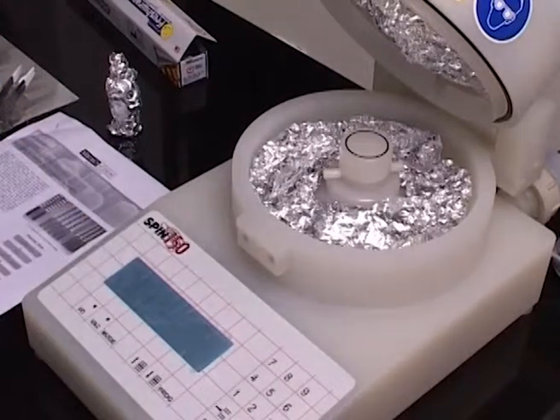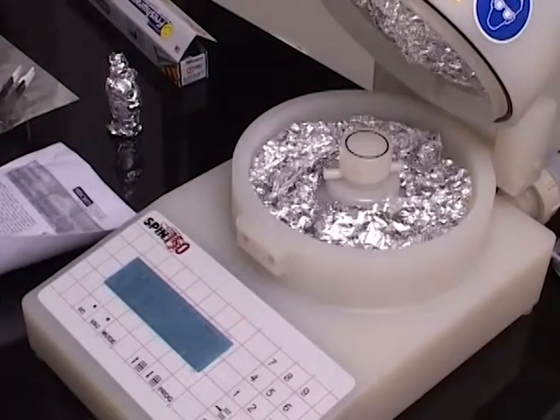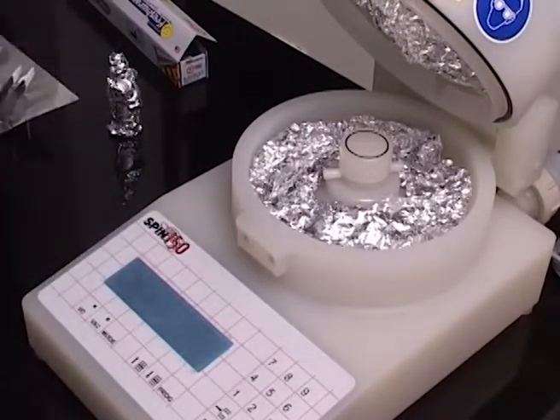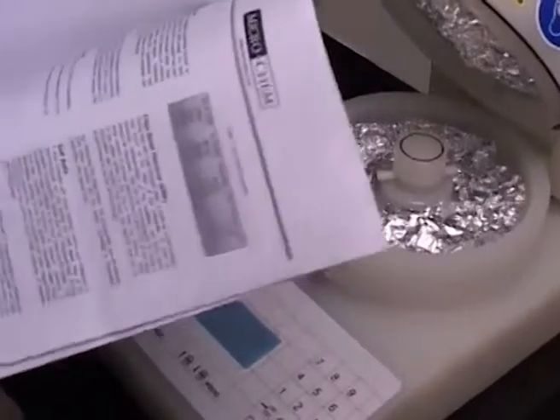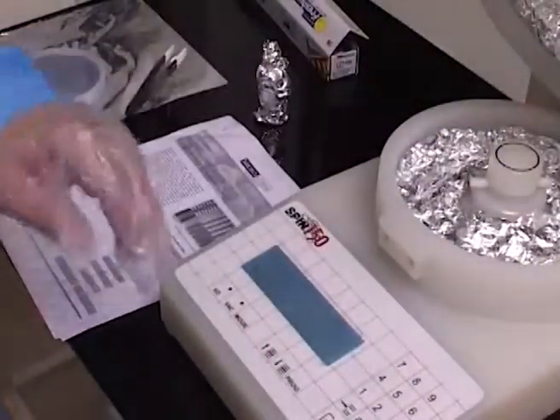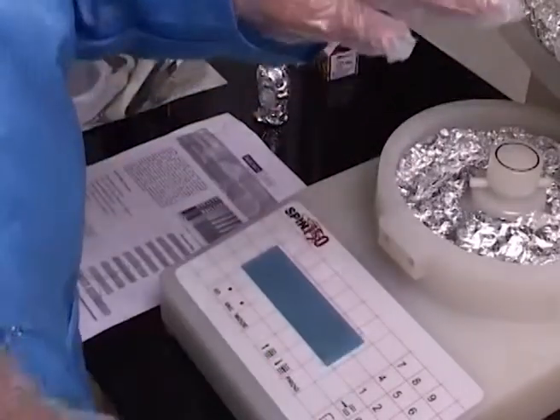In this particular example, as per the resist manufacturer specifications, the spin speed that we are using is about 3500 RPM, and the spin speed has to be attained with an acceleration of about 300 RPM per second. It also mentions that you have to hold at that spin speed for close to 90 seconds for the spin coating to be uniform. I would also like to illustrate that the resist, being a thick material, needs a little bit of time for uniform coverage over the whole surface.